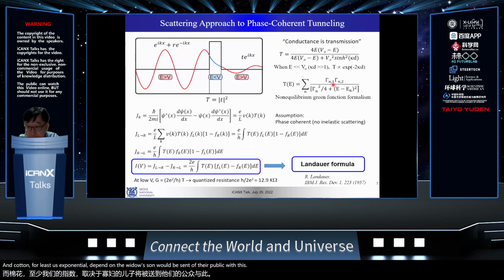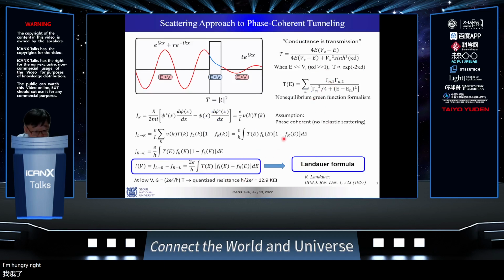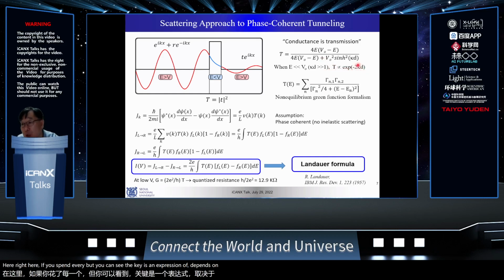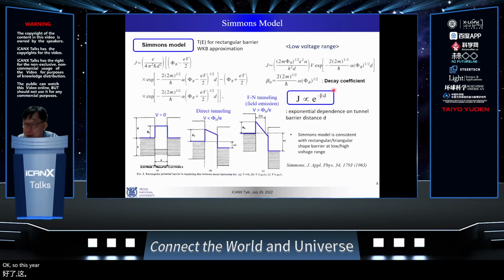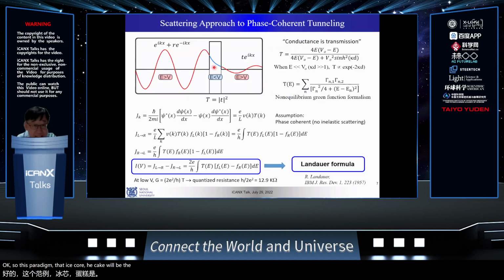So this beta value right here, you can see that T depends exponentially on D with a 2 kappa. So beta is like a 2 kappa. Okay, so this beta is called the decay coefficient. Basically, it tells how quickly the electron decays within the barrier. Insulating media decrease quickly, more conducting media decrease slowly.